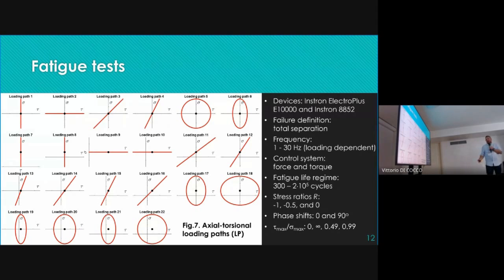We controlled force and torque, and the fatigue regime was roughly from 300 to 200,000 life cycles. And the stress ratio, like I said before, was from -1 through -0.5 and 0, and the phase shifts were 0 and 90 degrees.